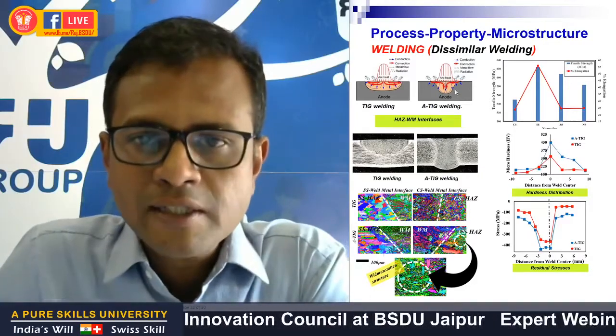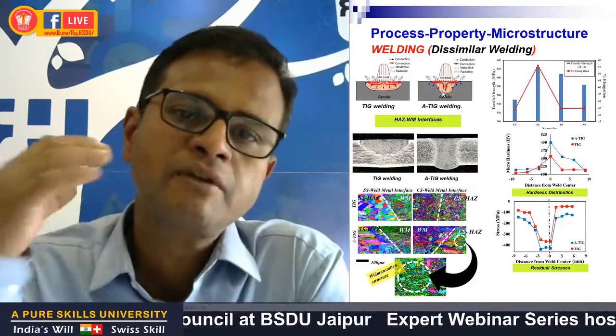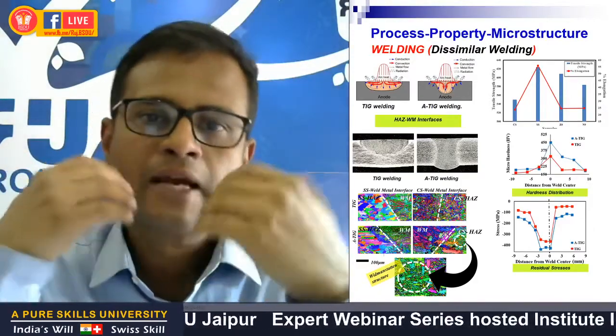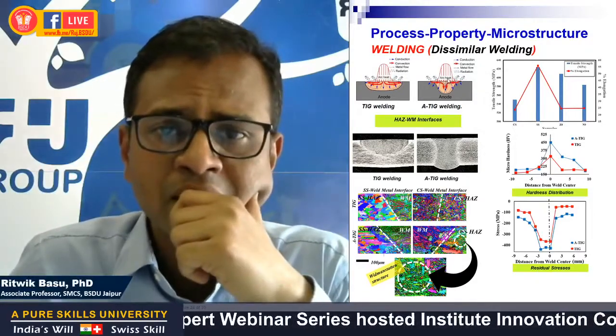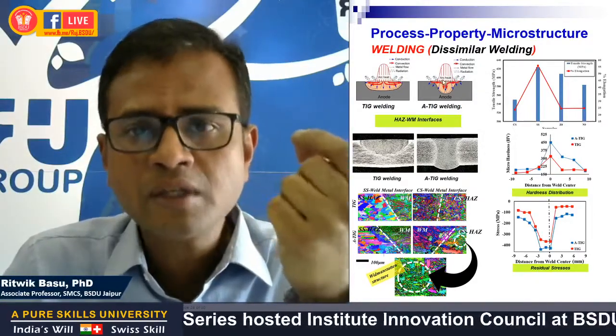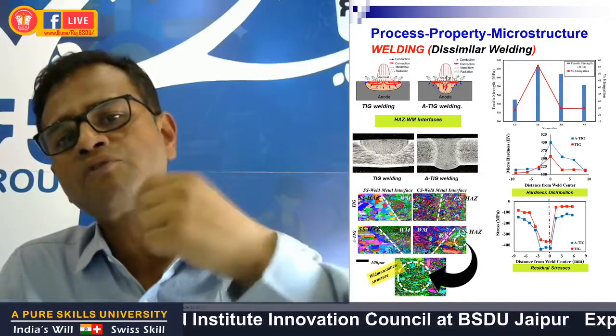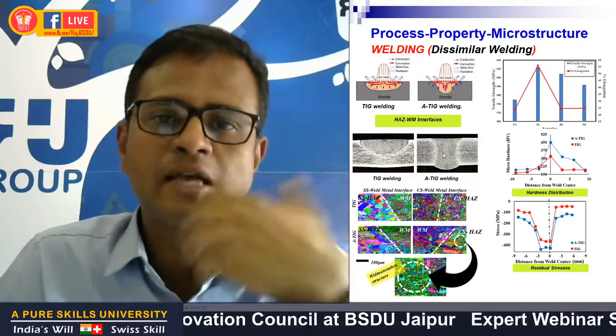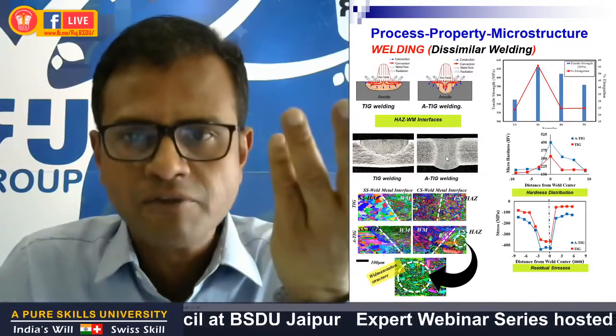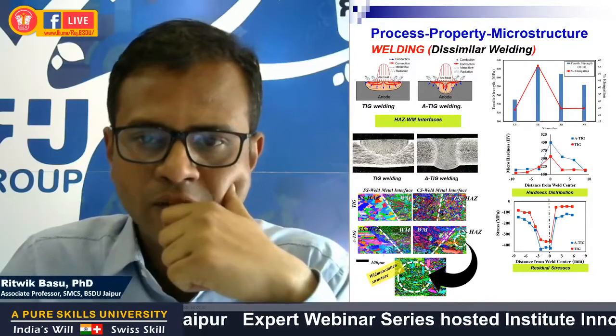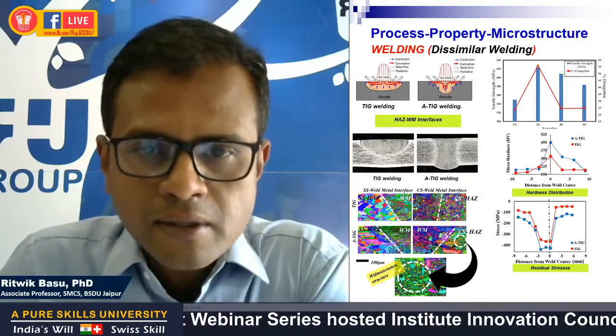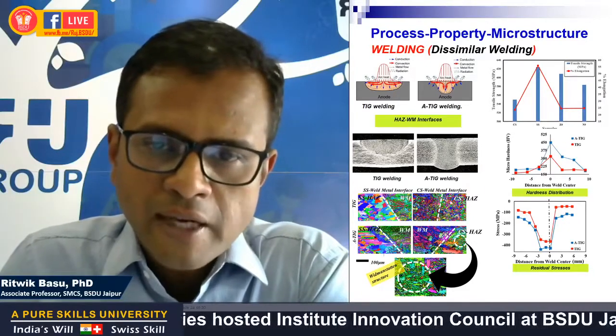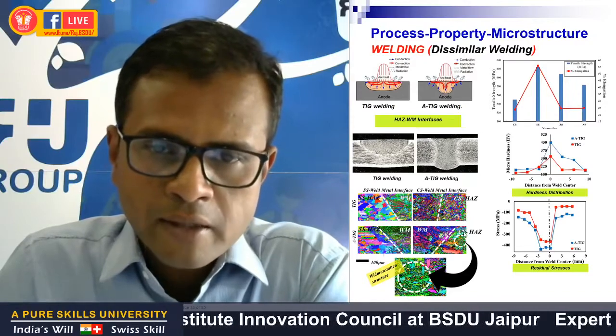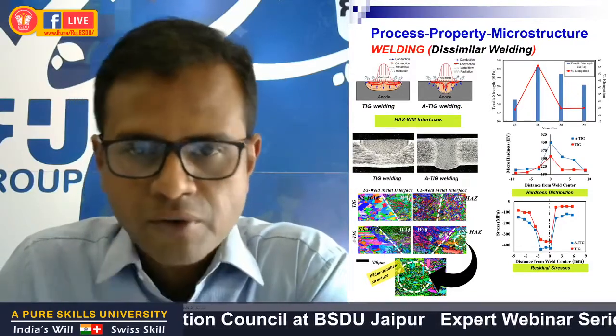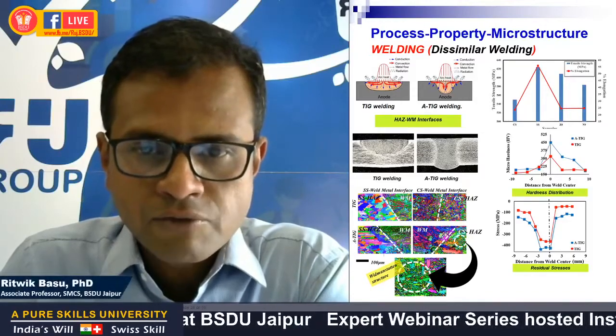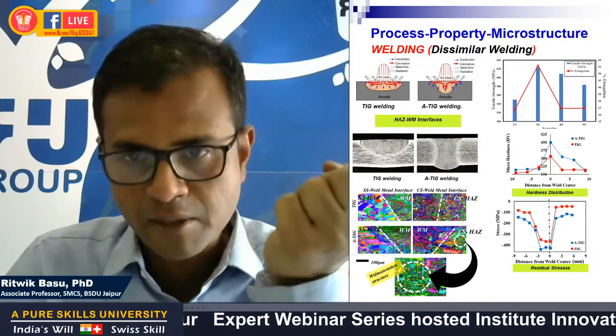So in the case of activated TIG welding, or A-TIG welding, an activated flux is applied on the material which is to be welded, and that leads to constriction of the arc, leading to increased current density in the anode root, and also this increases the arc forces on the weldment. So when welding stainless steel or any other steel through A-TIG welding, the cooling rates are significantly increased. It is seen that the heat affected zone of the carbon steel side in the case of TIG welding shows a more fine equiaxed ferritic microstructure, while the heat affected zone of the carbon steel side for the A-TIG welded specimen shows a Widmanstatten ferritic structure that introduces significant grain refinement.